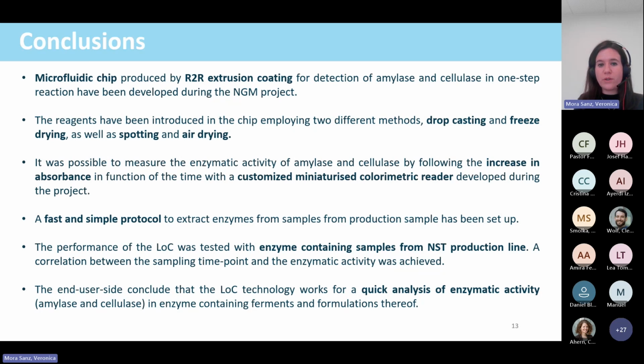It was possible to measure the enzymatic activity of both enzymes by following the increase of absorbance in function of the time with a customized miniaturized colorimetric reader also developed during the project. We also set up a fast and simple protocol to extract enzymes from the sample in the production line. And the performance of this LoC was tested with enzyme-containing samples from Naturstoff, and a correlation between the sample time point and the enzymatic activity was achieved.